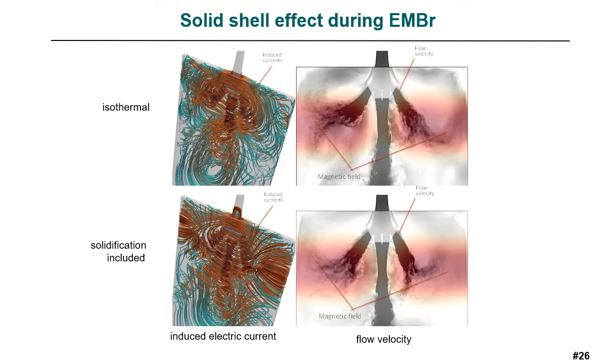In the conclusions, I would like to refer to one of the most important findings of the presented study. If the presence of the highly conductive solid shell is ignored in the isothermal simulation, that leads to significant flow instabilities since the induced electric current have to close through the liquid bulk. Considering solidification during modeling of the electromagnetic braking leads to partial flow stabilization, which according to the measurements reflects the reality more accurately. Additionally, it should be coupled with the proper deformation model for the solid shell.